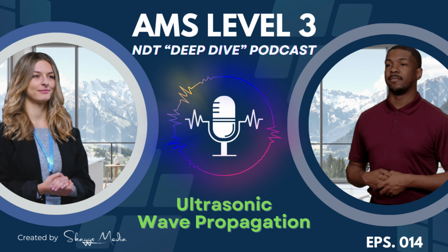Okay, let's shift gears slightly. We've talked about waves going through the material. What about waves that stick to the surface? Surface waves. Right, the most common one we encounter is the Rayleigh wave. These waves are interesting because their energy is really concentrated right near the surface, typically only penetrating about one wavelength deep. And the way the particles move is pretty complex. It's not just back and forth or side to side. It's an elliptical motion, kind of rolling backwards relative to the wave direction, like watching a buoy bobbing on the ocean. And a key thing about them is speed.